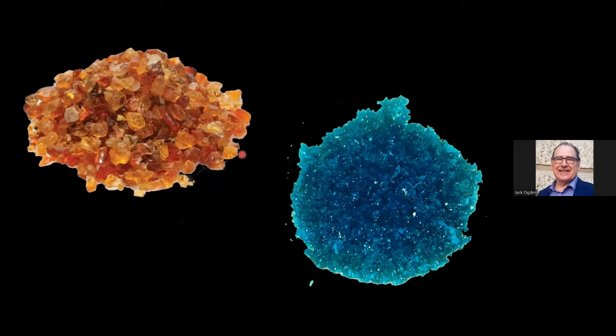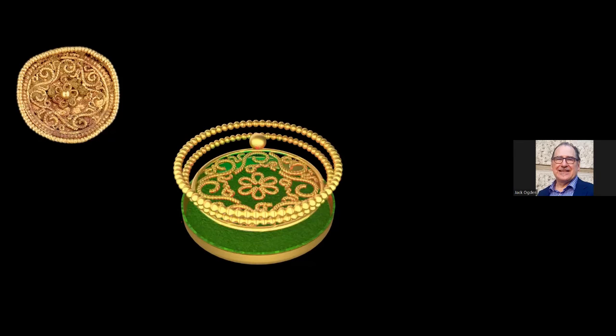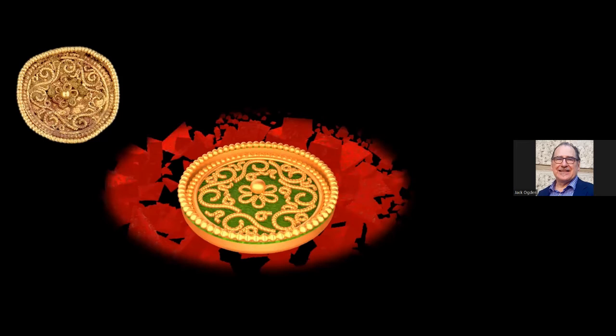Now, if you mix this into a little paste, this copper salt, we're using salt in the chemical sense, a copper compound with a water soluble glue, mix them together, and you then basically paint them onto the surface of where you're going to solder things on. You paint this mixture on, and then you apply the pieces into there. You then heat it in your furnace or over burning charcoal, bring it up to temperature, and something rather extraordinary happens. As the whole thing heats up, the copper acetate, or other copper substances, reduces, as they say in chemical terms, to pure copper. So the pure copper, if you like, comes out of the copper compound.